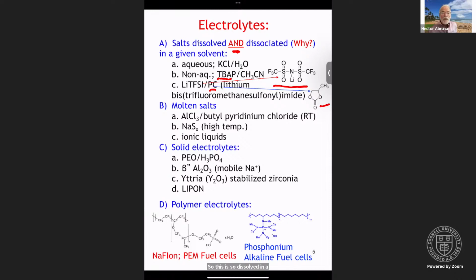You can also have molten salts. They come in a variety of ways. Aluminum chloride dissolved in butyl pyridinium chloride. This is a room temperature molten salt. They are, however, very sensitive to water and oxygen, so you have to be experimentally very careful. Sodium polysulfides is a high temperature electrolyte used in sodium sulfur batteries, typical of things that were developed at General Electric.